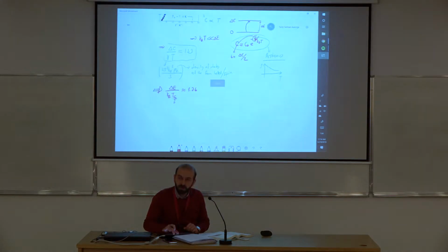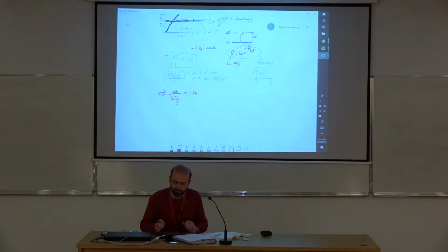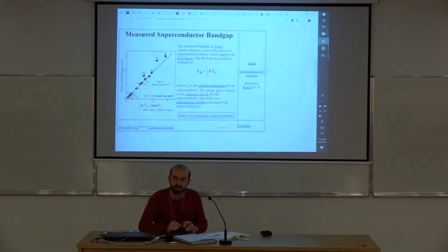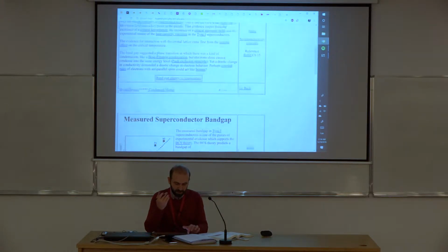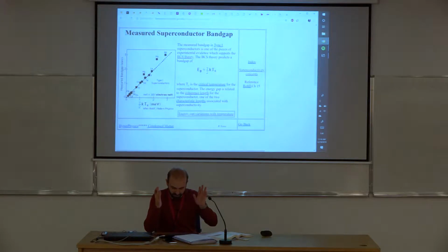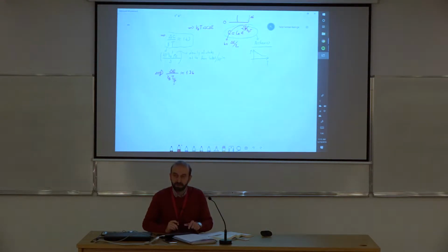All right. So what do you mean, like an ideal? Yes. Now, the idea here is that these impurities really do not affect the superconducting order. And when they do start affecting, it starts destroying the order altogether. The coherence length of Cooper pairs is so large that any such defects and impurities don't matter. And as we'll see in the Josephson effect, even if you insert an insulating material in between two superconductors, the superconducting order doesn't get bothered by such an insulator in between the superconductors.